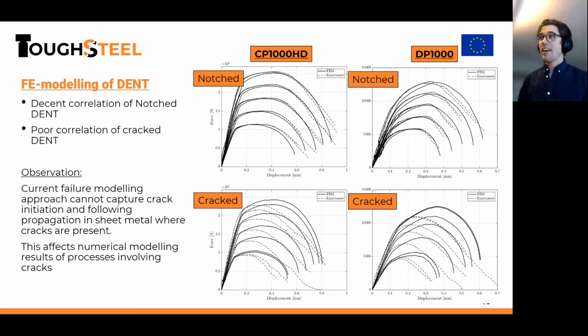But now to the dent modeling. Here you see the graphs to the right. On the upper row, we see the force displacement results for notched, that is undamaged, dent specimens, and we see the entire range of ligament lengths. We see that the correlation is good, at least until the end of the tensile testing, where you have a lot of material failure and fracture evolution. But on the lower row, for the cracked specimens, we see quite poor correlation. We see that the numerical results drop later than in experiments, which means that the fatigue crack grows and propagates earlier in experiments than in modeling. It's apparent that the modeling really cannot capture the crack initiation in the fatigue crack tip, which is why we have over-predicted force displacement results in modeling.